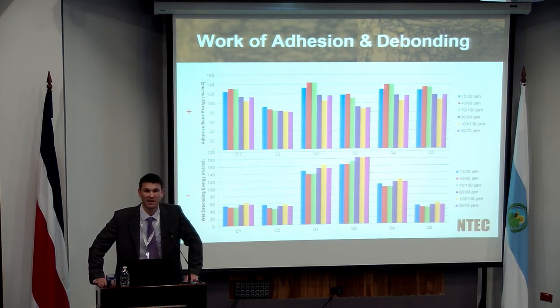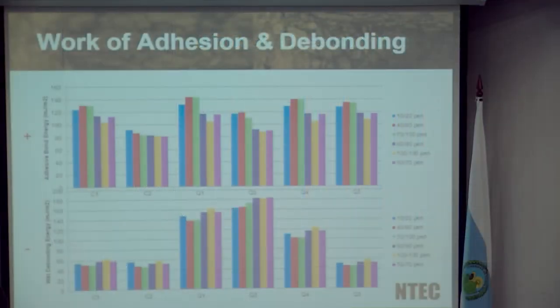So if I took exactly those same materials that I showed you previously, where we had very simple surface energy values for the bitumen and for the stone, and then I showed you a very simple set of equations which allowed us to work out those two adhesion parameters, one the dry, one the wet, we can plot those either in the form of a figure, as I've done in this particular slide, or in the form of a table. And straight away, we can see that there are massive differences, particularly when it comes to the wet adhesion.